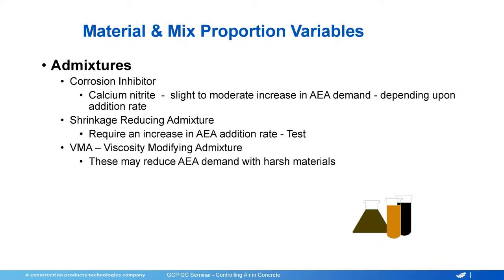So the viscosity modifiers can stabilize that air void area and make it easier for the bubbles to develop and to keep the bubbles in there. And this is where the rheology comes into play. So we can increase the viscosity of the mix enough so that we can keep the air bubbles in that we're trying to entrain, but not to the point where the mix becomes sticky, gooey, hard to manage, doesn't flow, those kind of things. So it's a balancing act, but we've been very successful using viscosity modifiers to make it easier to get air, especially in mixes where we can't get enough sand in the mix for whatever reason. Just makes it much easier to get that air and to get it stabilized.